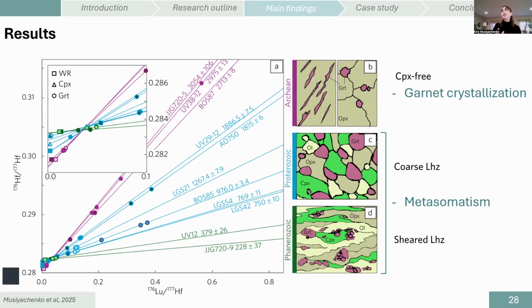If we now step back and look at all the results together, a slightly more coherent picture starts to emerge. We have our clinopyroxene-bearing lithologies here that already have a sink for hafnium. So lutetium-hafnium ages in these rocks are sensitive to the removal of those kinetic barriers, in other words, the introduction of a fluid or melt that enables re-equilibration. In these cases, lutetium-hafnium ages record the last metasomatic interaction experienced by that rock.